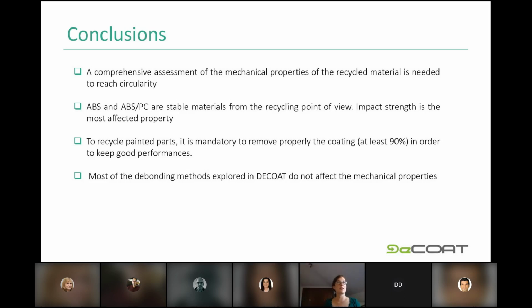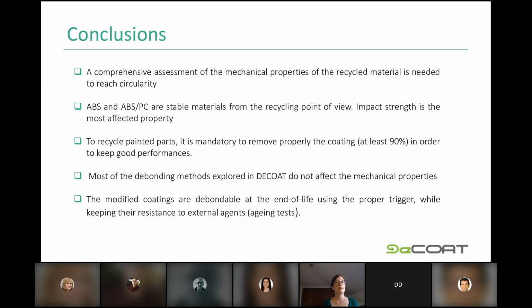Most of the debonding methods explored in the project don't affect the mechanical properties, so it's a good path to reach this goal. And the modified coatings are debonded at the end of life using the proper triggers, but they are able to keep the resistance during the aging, due to external agents during the use of the parts. So it's also okay to reach the very demanding requirements for both automotive and electronic use case.